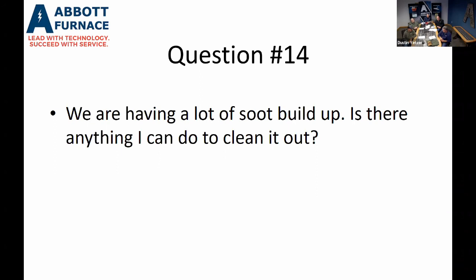Sometimes it's quite hard. So the other option is doing what we call burnout. And we do have a written procedure for this. If anybody wants it, glad to share it. But basically it's removing all the atmosphere out of the furnace, so it's just air inside. And this is done in a very controlled manner, introducing outside air, oxygen, into the furnace at an elevated temperature that will essentially burn that material up. Now, if this is the first time you're thinking about doing this and there's a lot of buildup, there's smoke going to come out of everywhere. So just be cautious, take it slow. But that's one thing that can help.